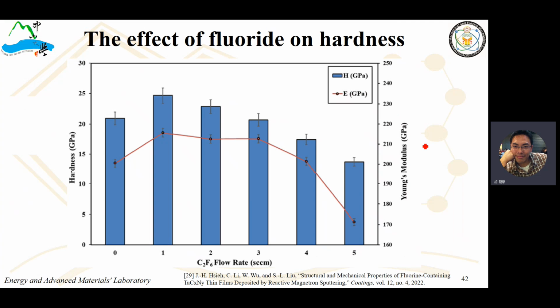This reference shows that when the surface is doped with fluorine, in this case fluorine gas, its surface hardness and modulus increase with the content of fluorine dopant, up to a specific limit. When the fluorine dopant is beyond that limit, the surface properties, hardness and Young's modulus, drop substantially.